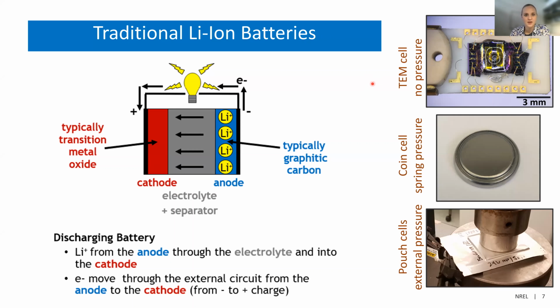To study this, we've been looking at 3 different configurations. We have our TEM liquid cell, which is an electrochemical platform that operates within the transmission electron microscope so that we can get nanoscale imaging of these processes. We've also done a lot with coin cells because they're easy to cycle and put together, and then to take the electrodes apart and image them separately. And then there's been work with pouch cells so that we can control the pressure instead of using just a spring in the coin cell, but we can use a load frame to then control that pressure.